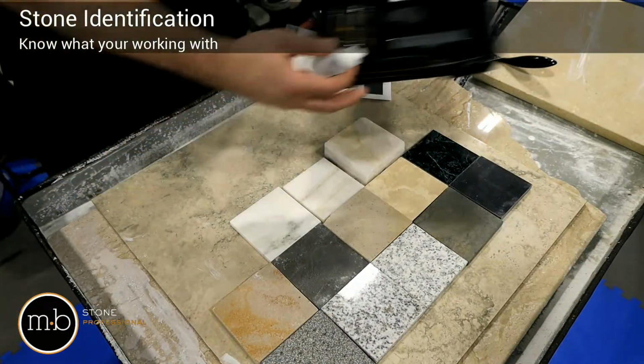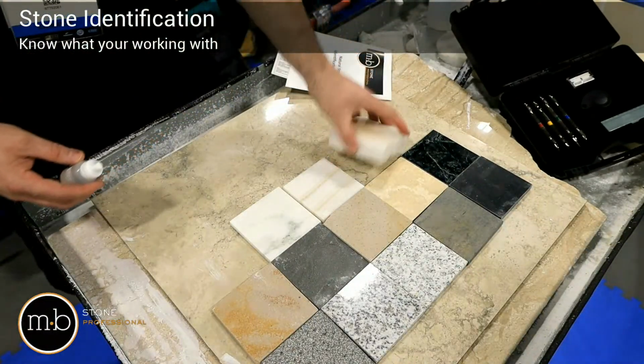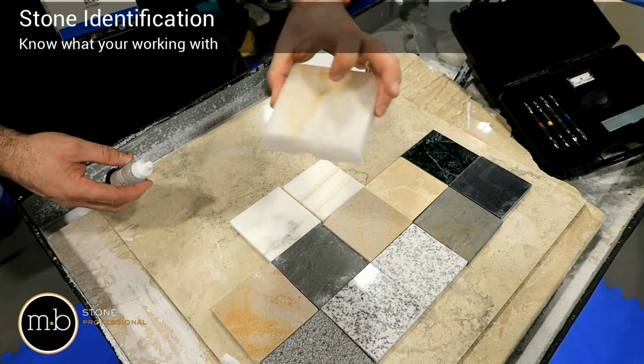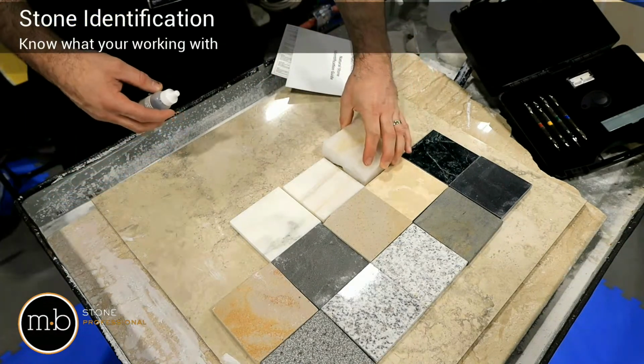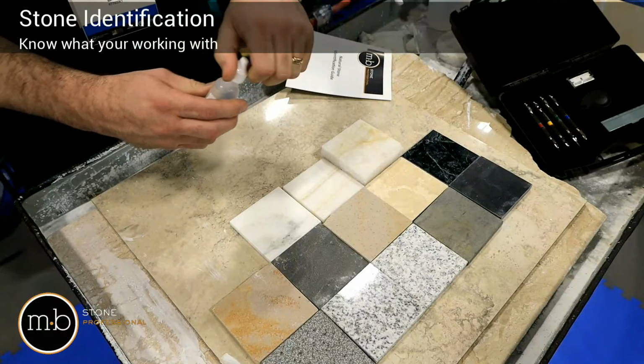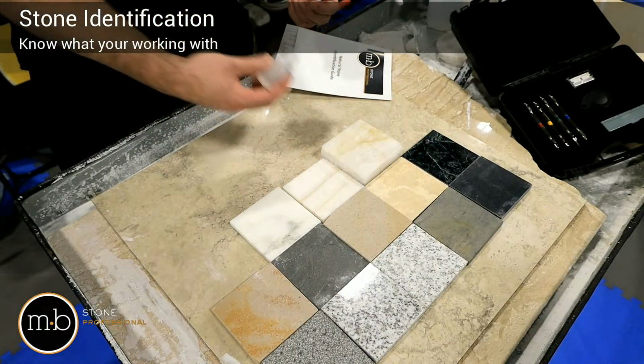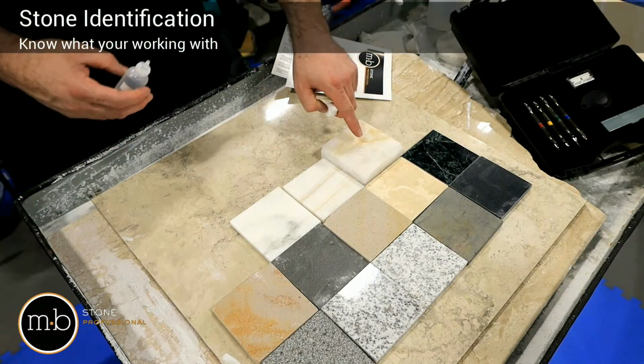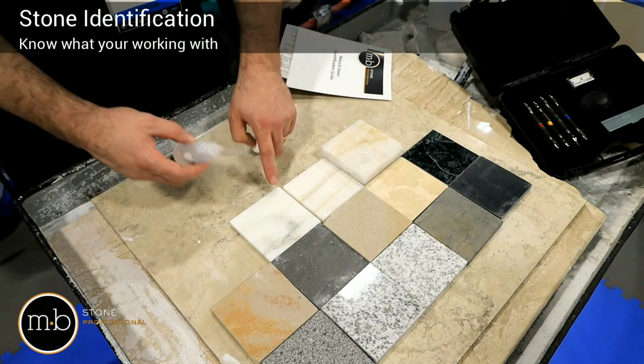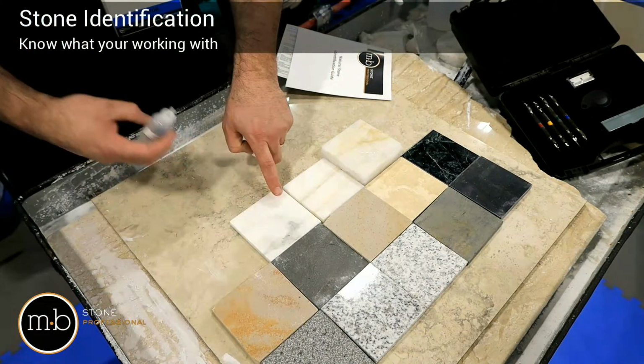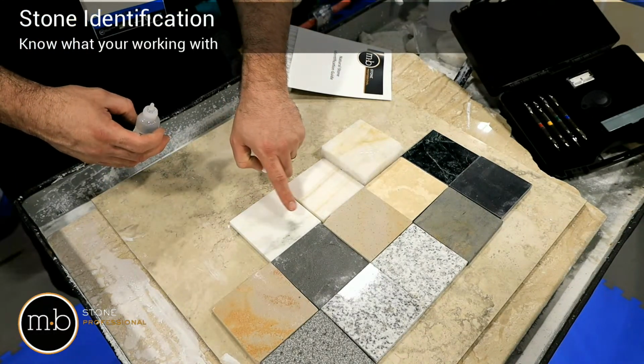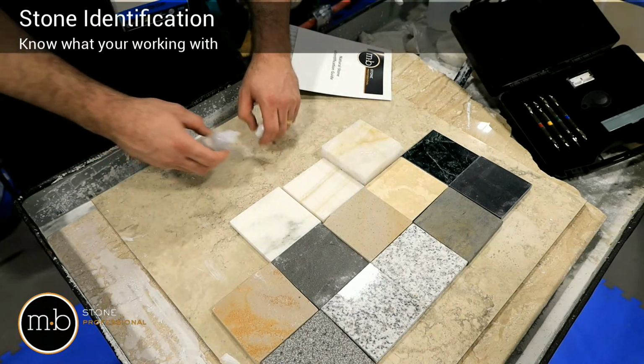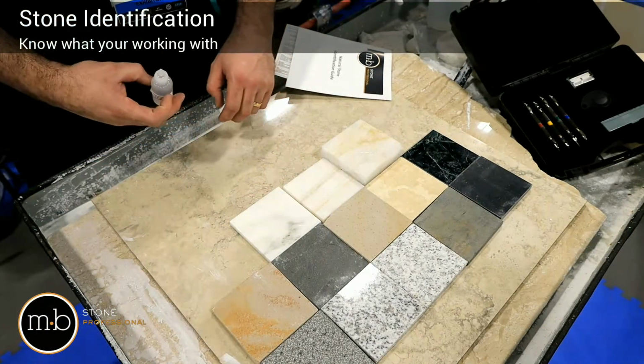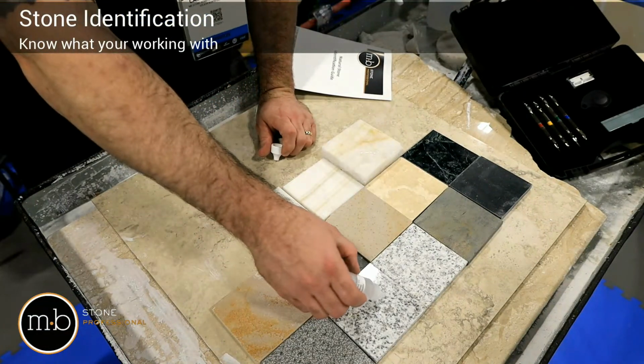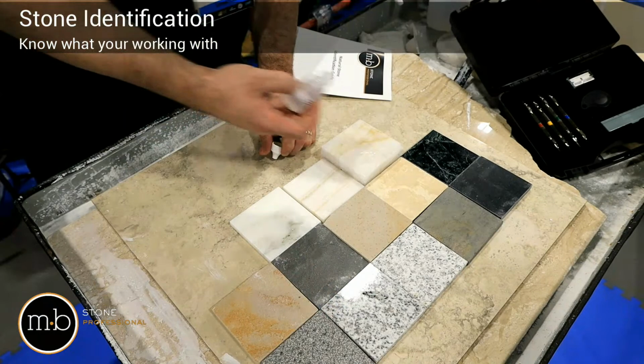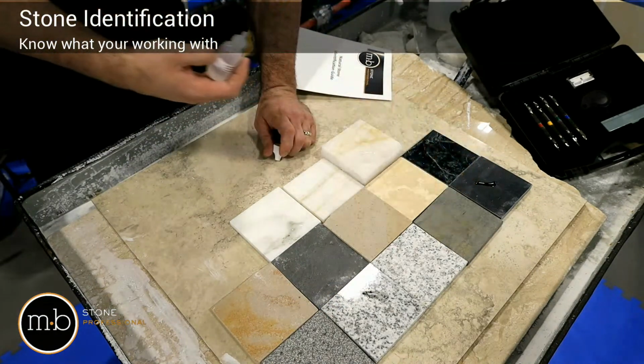So for instance, this quartzite, they have it labeled as champagne quartzite, similar to like Cristallo. If we put acid on there, there's no reaction, there's no fizzing, nothing like that. If we put it on here, you can see the effervescence and it starts fizzing on this onyx as well. On the polished granite, there's no reaction. Soapstone, no reaction.